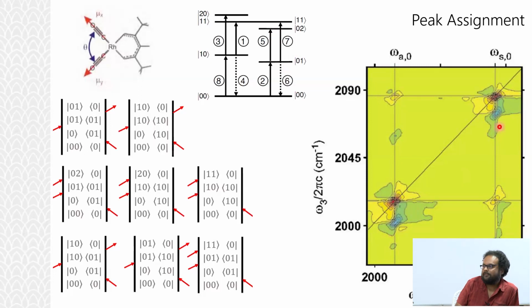Okay? Excited state absorption. Remember, you have two more excited state absorption features associated with the transition from 0,1 or 1,0 to your 1,1 state, the mixed state, and those are these little guys. Okay? So in this one experimental spectrum, it's spectacularly pedagogical to understand and assign the different features that you can observe. Very, very remarkable, right?